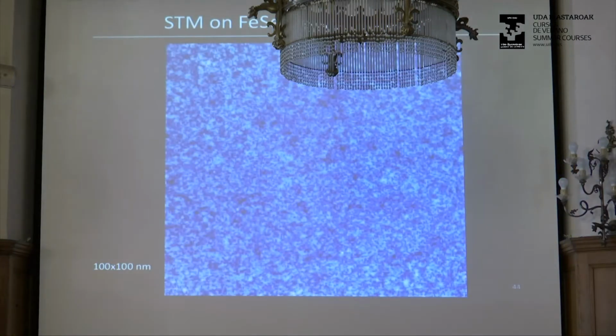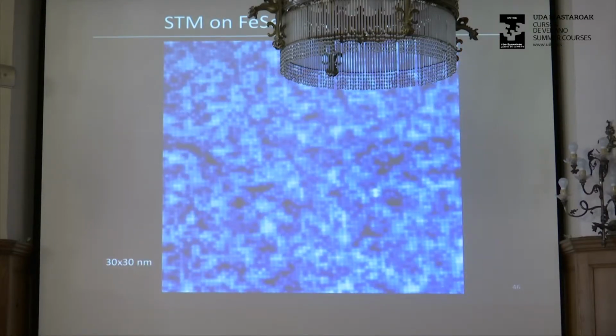Then our experiments had to wait until we got these beautiful samples from Genda Gu. Now this is a giant, for us, giant field of view, right? It's just about 100 nanometers. And if you squint, you can see the atoms. In fact, I'll show you a zoom in. In this entire field of view, I think there's maybe one excess iron here, but maybe none. Okay, so if you zoom in, you can see the atoms. All the contrast here comes from the fact that you have selenium and tellurium. In fact, you can count how many seleniums and telluriums you have. One of them shows up as a bright dot, and the other shows up as a dark dot.